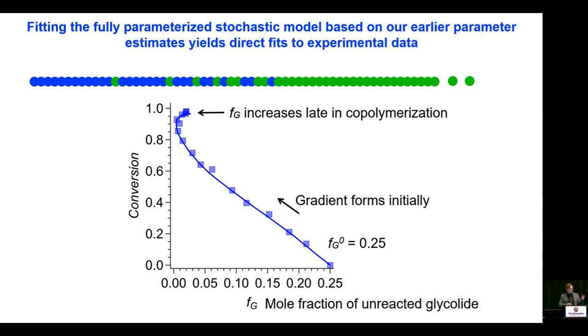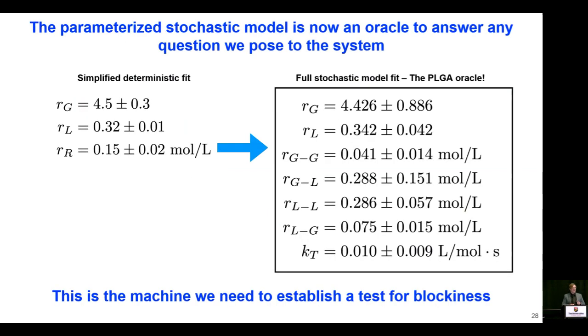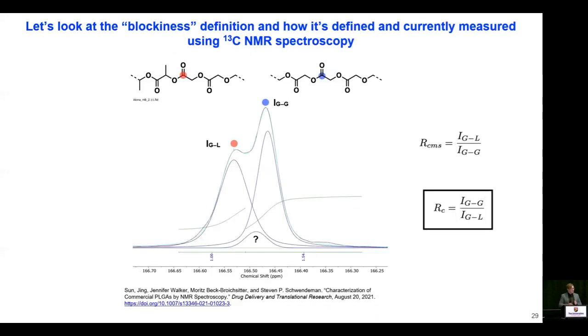And what's happening here is that we initially have that gradient that forms, but then through transesterification, eventually we enrich glycolide towards the chain end where the catalyst is, and now glycolide can equilibrate with its equilibrium solution concentration. And so what you see there is this delayed equilibration of glycolide, and the model captures that, which is really cool. So now we have our fully parameterized model for PLGA, which really gives us a view under the hood of what's happening. We have essentially an oracle now for PLGA. We can ask almost any question that we want and get an answer.